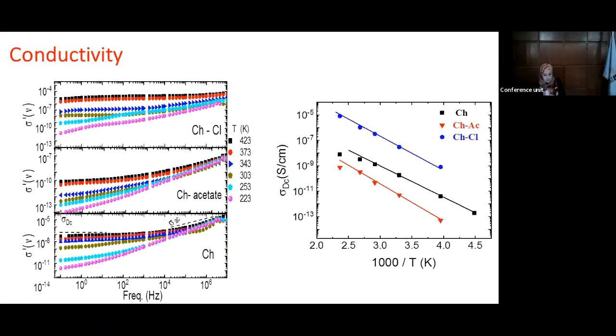If we check the conductivity, chitosan, like any insulating polymer, has something like 10 to the minus 8 and decreases downwards with temperature. For chitosan-based acetate, it is more or less similar to chitosan, while for chitosan-based chlorine, the conductivity increased by something like four orders of magnitude. We picked the DC conductivity and found that all of them show Arrhenius-like temperature dependency.